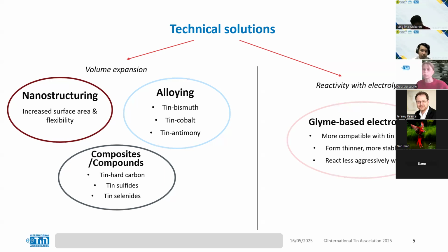If we look at the issue of reactivity with the electrolyte, there have been some solutions developed, such as the development of glyme-based electrolytes. These are more compatible electrolytes with tin anodes specifically. These electrolytes form thinner and more stable SEIs and react less aggressively with tin. So we don't get the same issues that we were seeing with the more conventional electrolyte materials. But it's important to note that tin anode research is less advanced than hard carbon research, for example. But further research and development could boost tin anodes to be even more competitive because of the unique advantages of tin in this scenario.